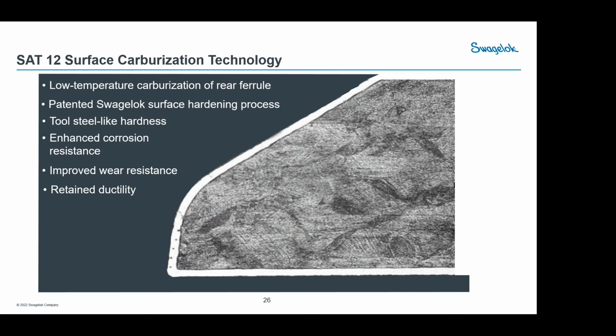I mentioned SAT12 earlier. SAT12 is a process we use, which is called low temperature case carburization. What this does is we take stainless steel. This is a ferrule nose, if you see it in cross section. What we do is we strip off the oxide layer to allow us to force carbon into the surface. The carbon gets super hard, but we do it at a low enough temperature that we don't create carbides. That gets us tool-like hardness, and then the ability to have high levels of corrosion resistance.